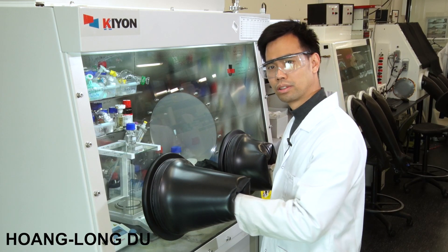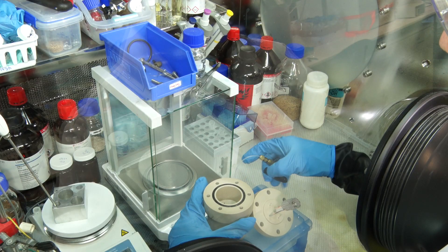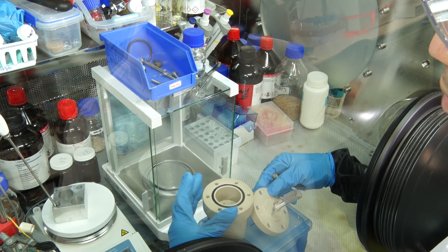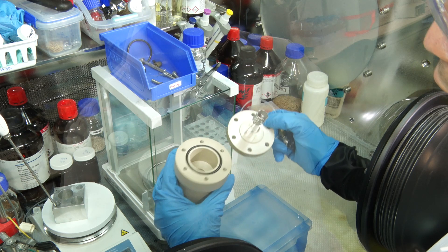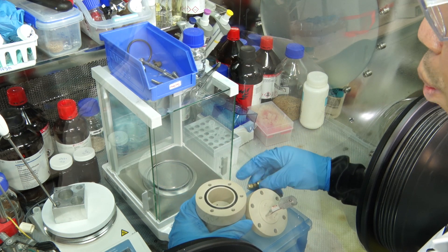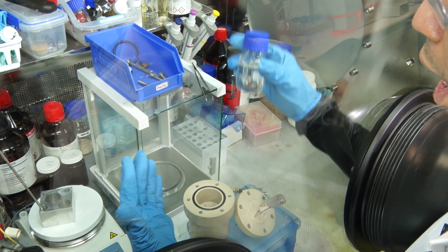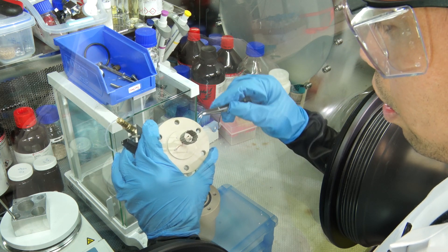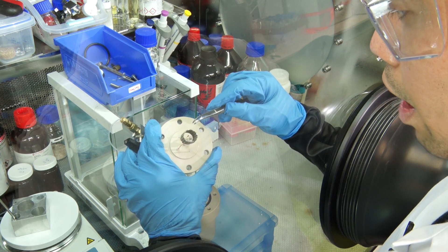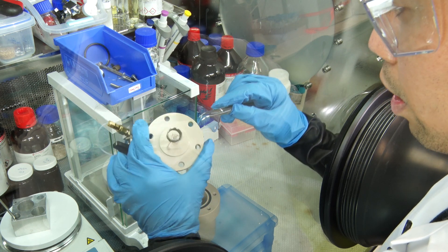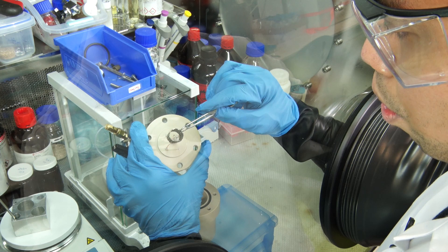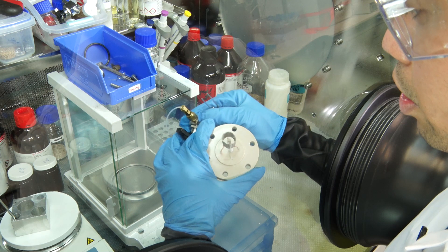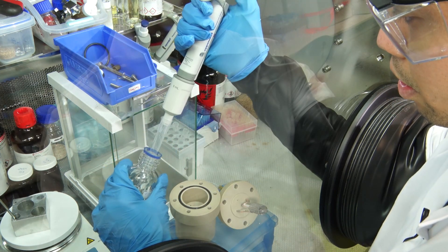So here we are in an argon-filled glove box. We don't want to handle our cell in the air because that can introduce nasty contaminants. Our experiments are carried out in the cell, such as this, with a fixed quantity of nitrogen gas and electrolyte. Here is the copper working electrode with the stainless steel outer electrode. It is an anode. This is the copper reference electrode, which allows us to monitor what is happening on the surface of the copper electrode. Fill up the cell with the electrolyte.